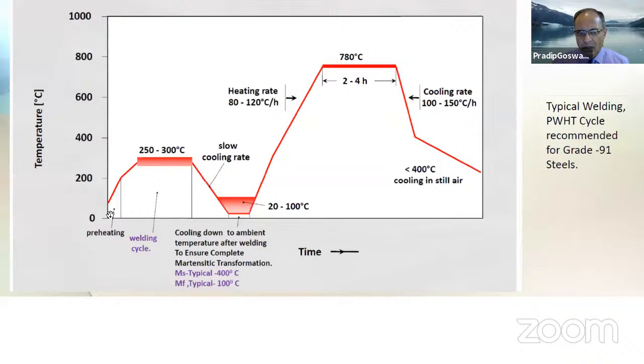So what we see here is that the recommendation is preheating, welding, martensitic transformation, NDE, QA, post-weld heat treatment, and then final cooling to the ambient temperature after post-weld heat treatment. It should go in one complete, continuous cycle. Now, somebody may say, why not break it up? We'll talk about that later, what the complications and difficulties one may face could be.